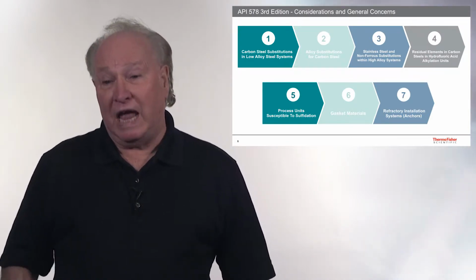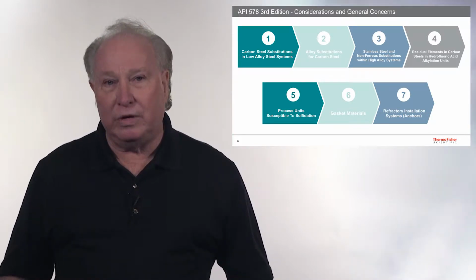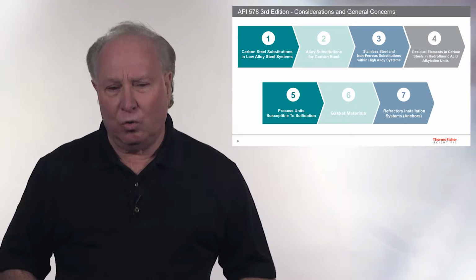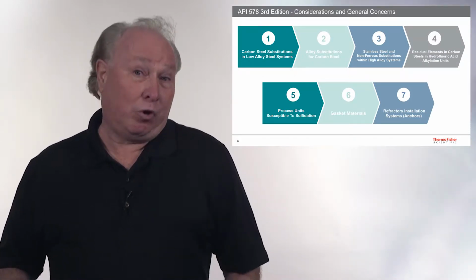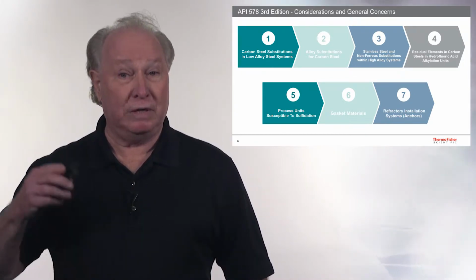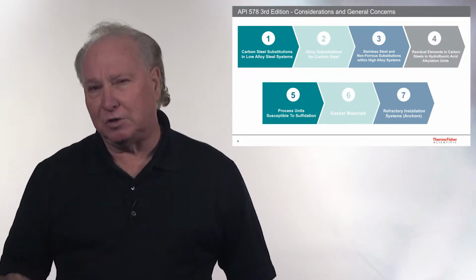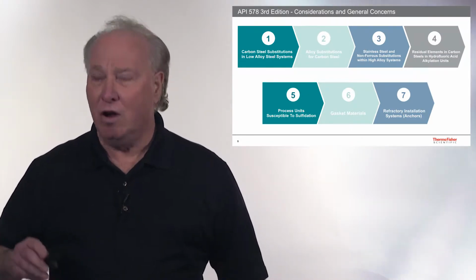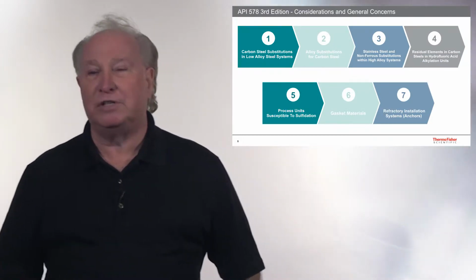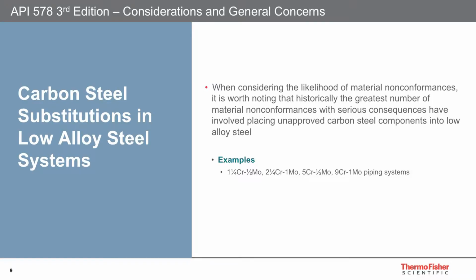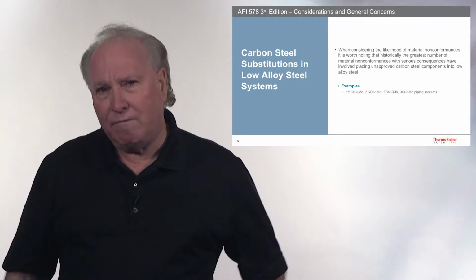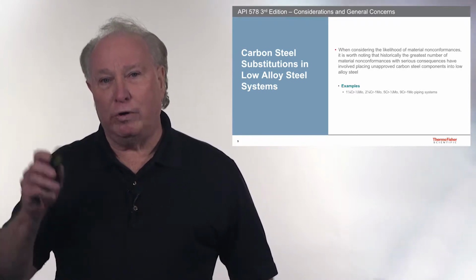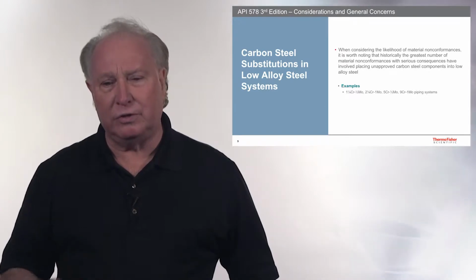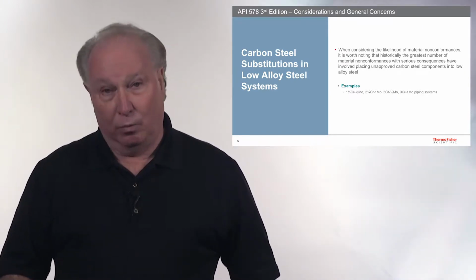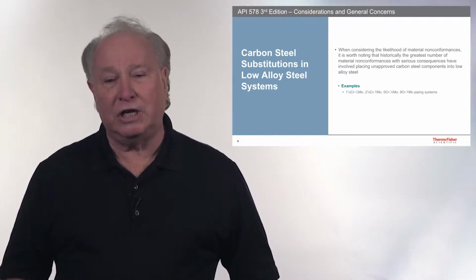In HF alkylation plants, we have carbon steels, and you have hydrofluoric acid going through it, and sometimes the residual elements, we'll talk about those, really create a problem with corrosion. Big corrosion problems in all of these plants where you have hydrocarbons going through it is where sulfur comes in. It's called sulfidation. I'll explain that in the units of sulfidation corrosion. Gaskets are there, refractory anchors, we cover all of that. So what about these carbon steel substitutions, low alloy steels? They all look the same, but if you don't check it to see it has 1 1/4 chrome, half moly, and 5 chrome, 9 chrome, it's not going to do a good job for you, because high temperature and flow creates corrosion, and that corrosion and just ferrous materials can be very, very bad, and we check that all the time. And positive material identification technology can do a great job on that.